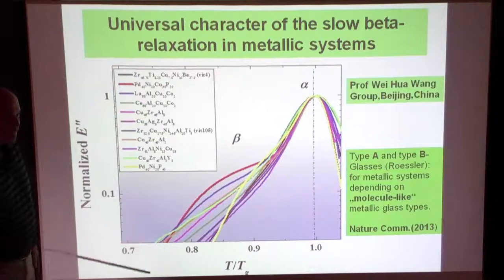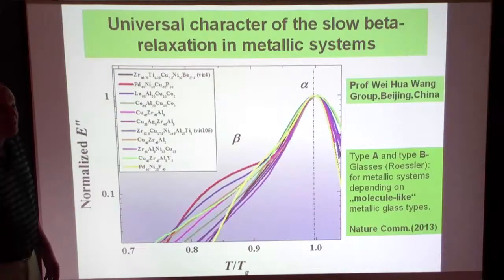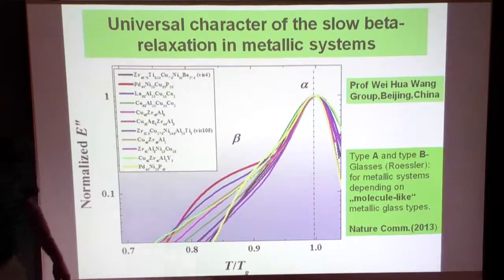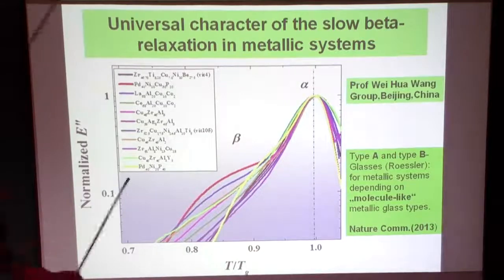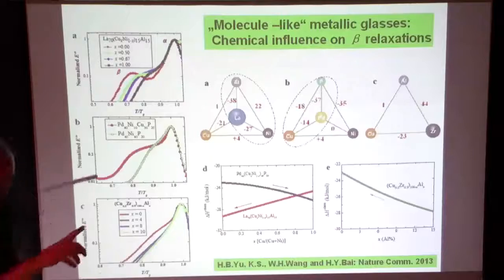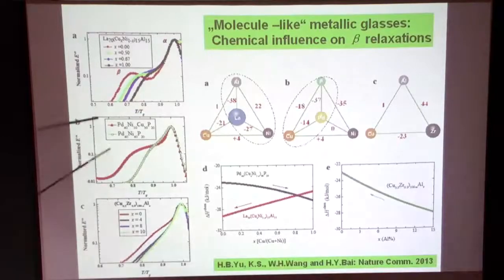But this is why this diffusion constant is measured in the liquid, with inelastic neutron scattering, Petry and others. The reason is that there are barriers you have to jump over. Let me show the next picture, and then I will discuss it, and promise not to come back. Here's an example. Palladium, nickel, copper, phosphorus, the red curve, compared to the green one, which is palladium, nickel, phosphorus alone. You cannot read the numbers properly. So you add copper to the system, and then the peak shows up.